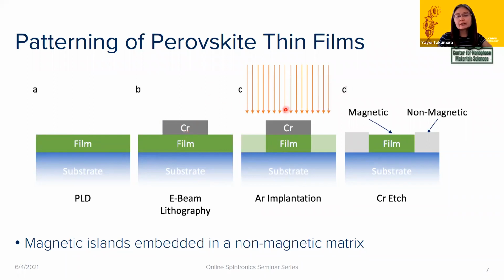And then we flood implant the whole sample with argon. The choice of argon is just that it's an inert element, so it's not going to chemically dope the material. And what happens is that where the film is unprotected, the argon ions come in and amorphize that part of the film, but the chromium layer is thick enough that all the argon ions get stopped by it, and the film underneath is unaffected. And so when we remove the chromium afterwards, what we end up with is these magnetic structures surrounded with a non-magnetic matrix, right?